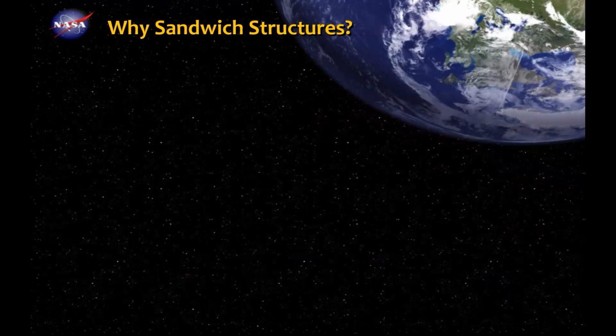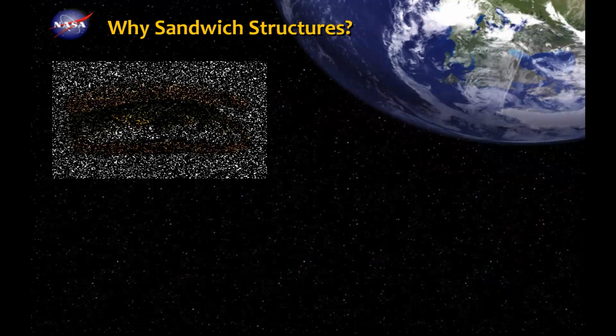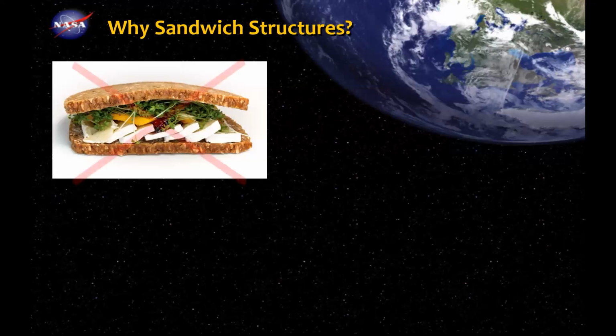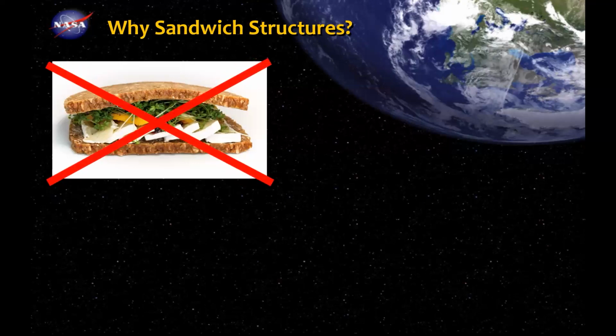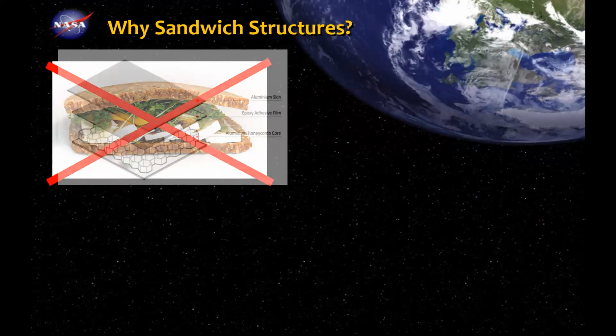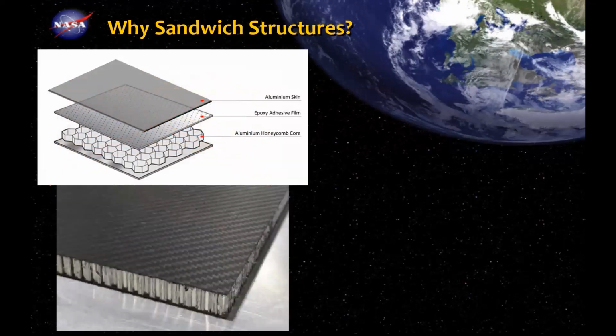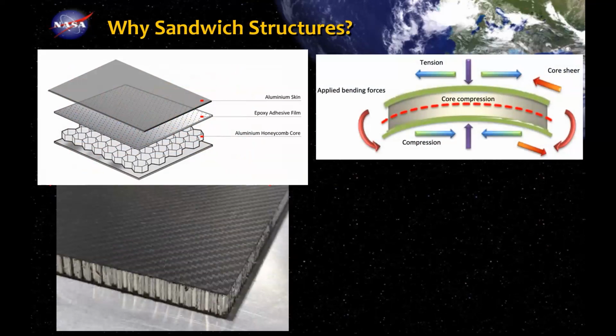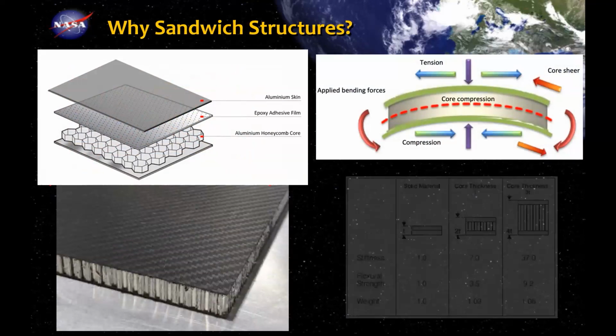And so what happens is we think of stiffness commonly driving a lot of our spacecraft structures. So that puts us to sandwich, which is on this chart. And so if you can animate through this, oh, sorry, I hit the down arrow, not sandwich, bad joke. Composite laminate sandwich. So when we put aluminum honeycomb core in, my bending stiffness goes up substantially. And for many applications, you have a massive benefit of increased bending stiffness.